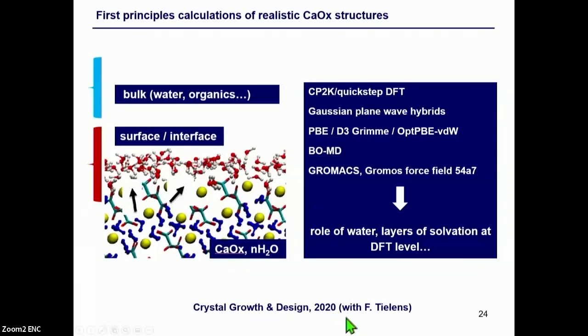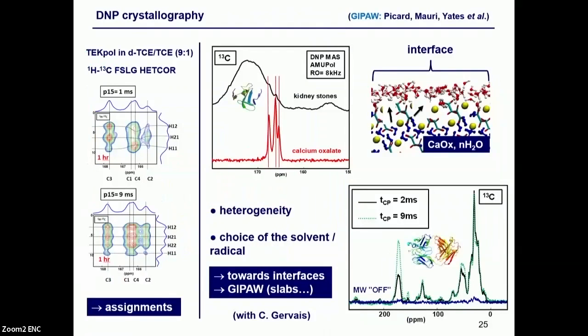Here, it was published rather recently in collaboration with F. Tielens. Here are some keywords of the methods we used, and we demonstrated in this case a particular role of water, and also the fact that the first layers of solvation had to be treated at DFT level. And then it's possible to go back to DNP experiments. You can do assignments by combining this structure prediction with GIPAW, and we had yesterday a beautiful talk by Jonathan Yates. And here, just a two-dimensional experiment, 1 hour experimental time, and the possibility to completely assign the proton and the carbon-13 in the monohydrate.